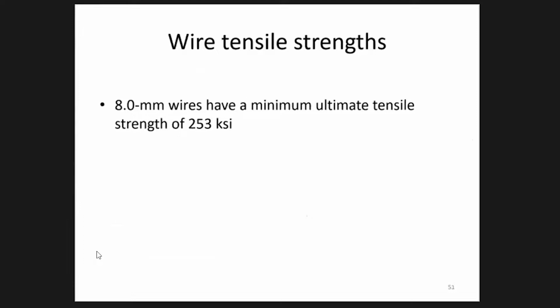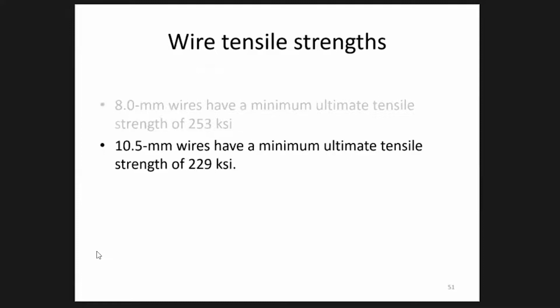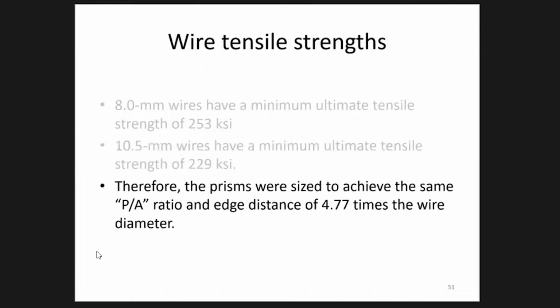And the strength that we tension the wires to, one of the things I wanted to note: when you go to larger diameter wires, the tensile strengths tend to decrease. For a 5.32 millimeter wire, you can get up around 270 KSI, 275 KSI. When you go to an 8 millimeter wire, you have less reduction of area, so you get 253 KSI, about the maximum that a producer would guarantee. And for 10.5, we're down to about 229 KSI.